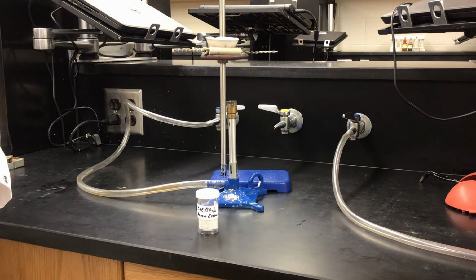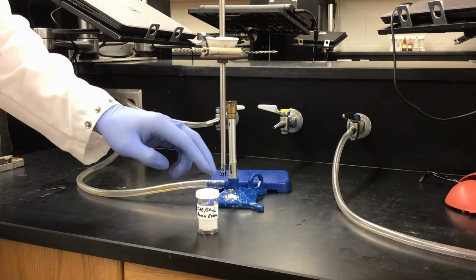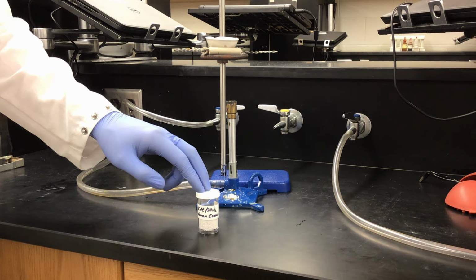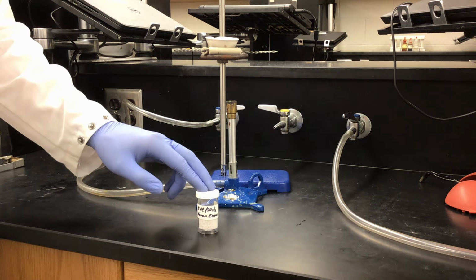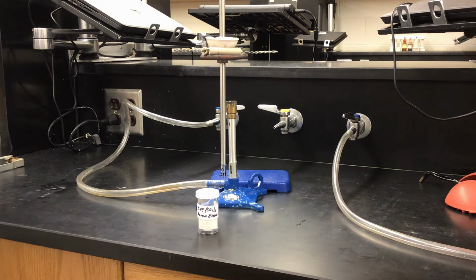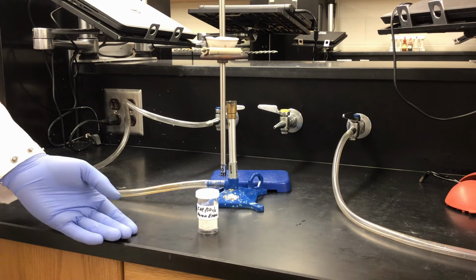Here is my potassium aluminum sulfate. Now that we had the final mass, we went through and calculated our percent yield. We found that we have a percent yield greater than 100%, which means we need to question what has happened. Since we know that we shouldn't be able to achieve a percent yield greater than 100%, I have theorized that we have created a hydrated salt. This means that there is water still stuck inside our crystal complex of our potassium aluminum sulfate. In order to prove this, I need to dehydrate my material.